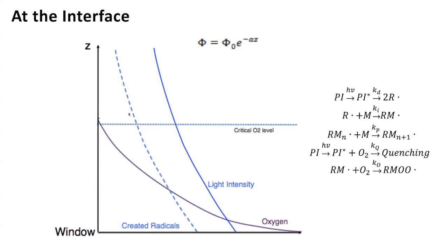But we all know in free radical polymerization, as we're classically trained, if you want to do a free radical polymerization, you degas your monomer. You're doing it because you're removing oxygen. And we count on oxygen as an inhibitor, especially during shipping of resins, so that they don't prematurely polymerize. So we're not removing the oxygen during this free radical polymerization, but as the light decomposes a photoinitiator, it generates a radical pair. That radical pair's rate of reaction with oxygen is far greater than the forward initiation of the polymerization.